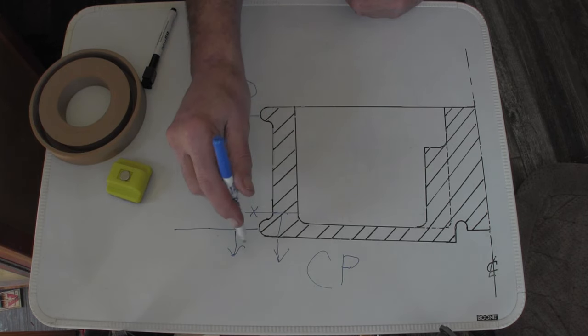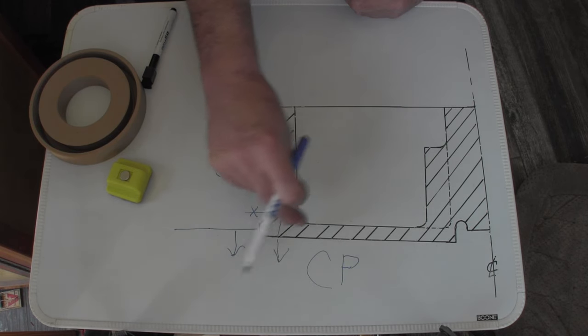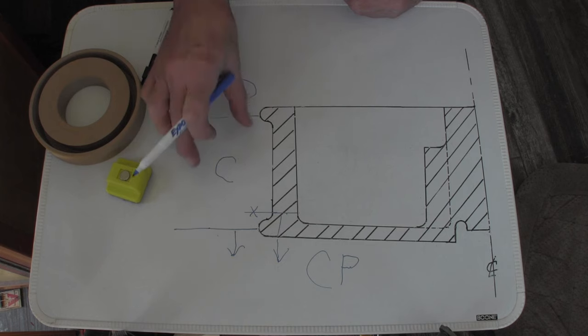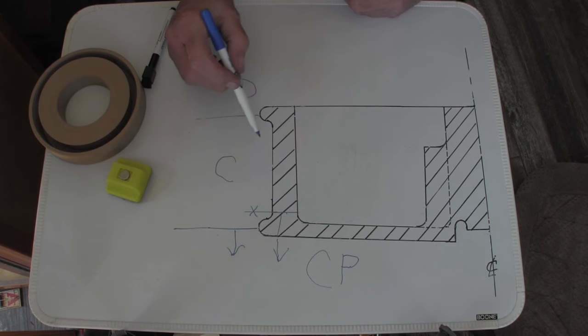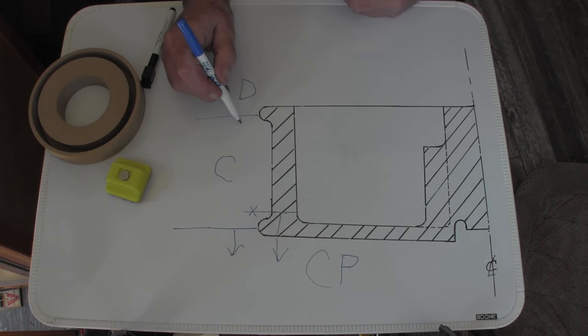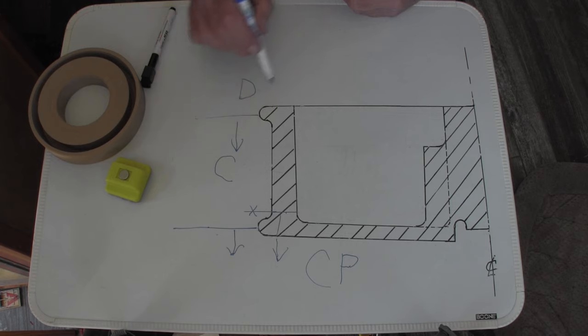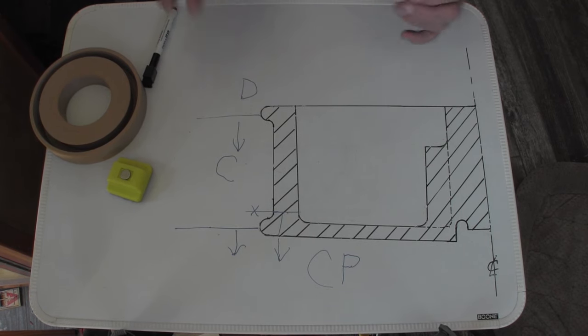You know, you'll probably end up pulling the cope mold off, and then you pull this out of the cheek, and then the cheek can lift off of this, and the cheek would lift out that way. Drag stays in position. You never have to touch a drag again once it's rammed up and rolled over.